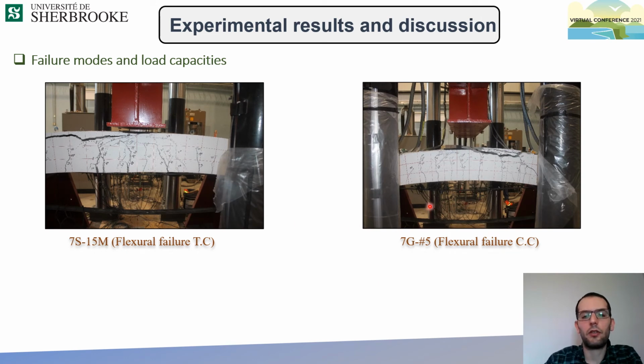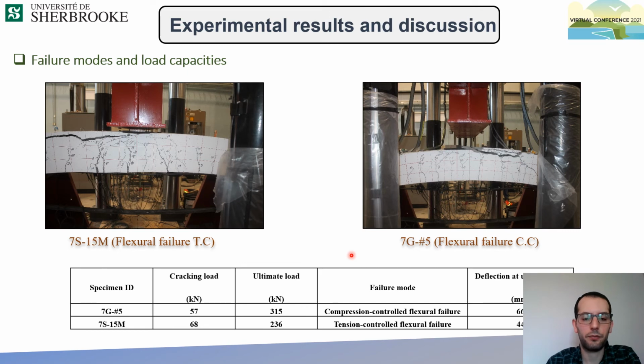The ST reinforced and GFRP reinforced specimens followed a typical flexural behavior with appearance of flexural cracks. After that, in the ST reinforced specimen, after yielding of the reinforcement, concrete crushing happened, which denotes the tension controlled flexural failure. The GFRP reinforced specimen also failed by concrete crushing, which is a favorable failure mode in GFRP reinforced flexural elements. The ultimate load in the GFRP reinforced specimen was higher than the ST reinforced one, and also the ultimate deflection.